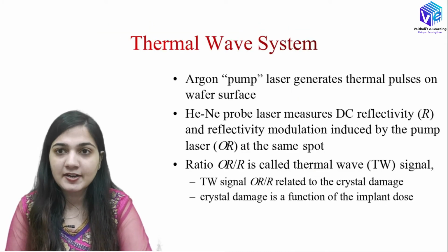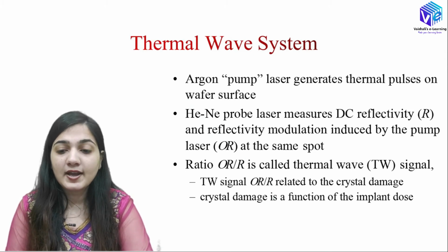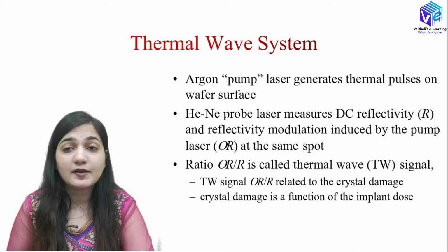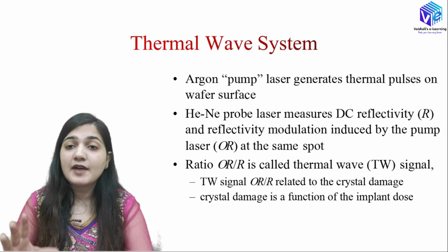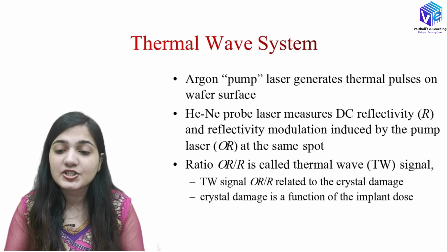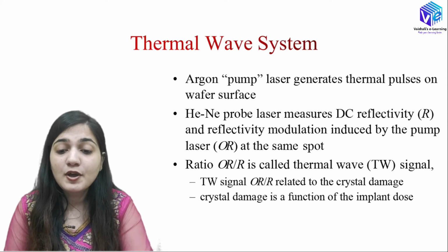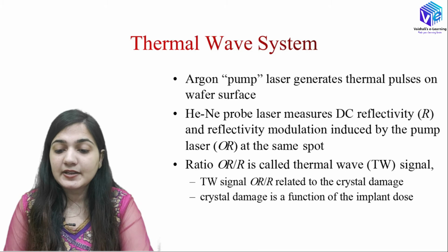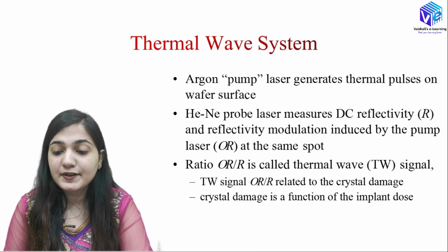Now coming to the second method, which is the thermal wave system. Here I will be using the argon pump laser, which generates thermal pulses on the wafer surface. I need to measure them. The helium neon probe laser measures the DC reflectivity and the reflectivity modulation induced by the pump laser at the same spot.